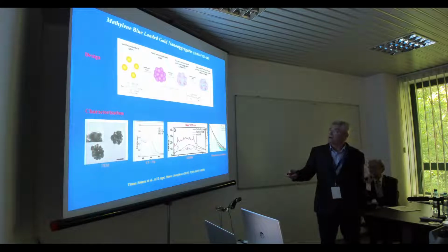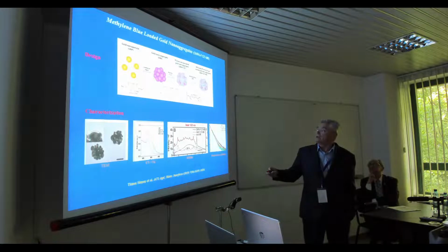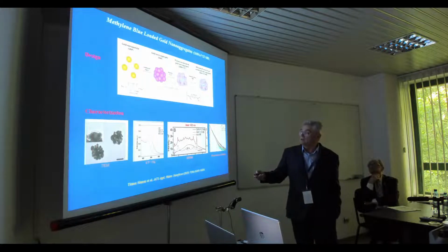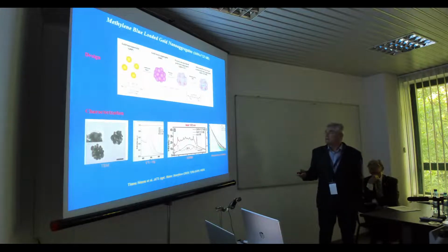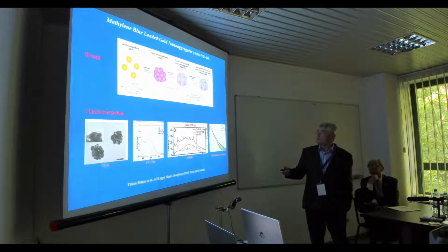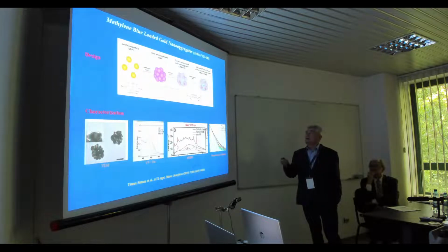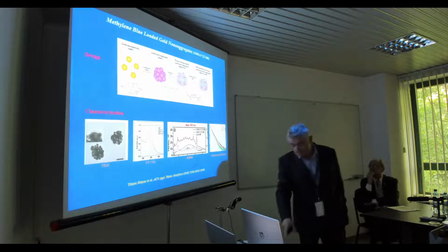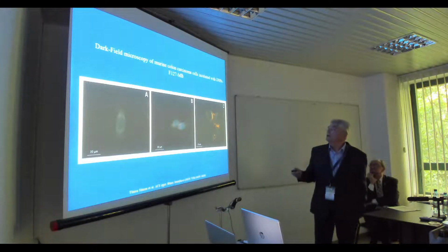Look here: individual nanoparticles in red, then a small cluster of nanoparticles a little bit shifted to 600, then here the presence of the methylene blue spectrum, the fluorescence emission. Then you can characterize better in solution. This was done first of all in solution, then was tested and checked on the cells.